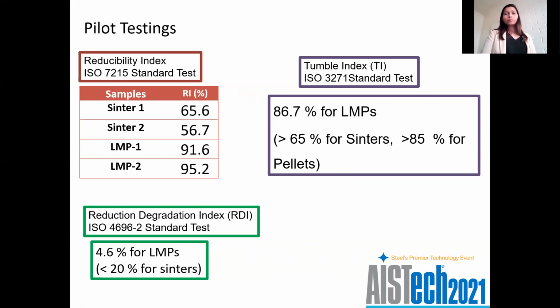Those are really excellent. For the tumble index, the standard test involves tumbling 15 kg of samples at 25 RPM for 200 revolutions, and then after tumbling, the products are sieved, and the plus 6.3 size fraction is called the TI. For LMPs, it was about 87 percent. The acceptable TI for sinter is more than 65, and for pellets more than 85. So the TI of LMPs is similar to pellets and more than sinters.